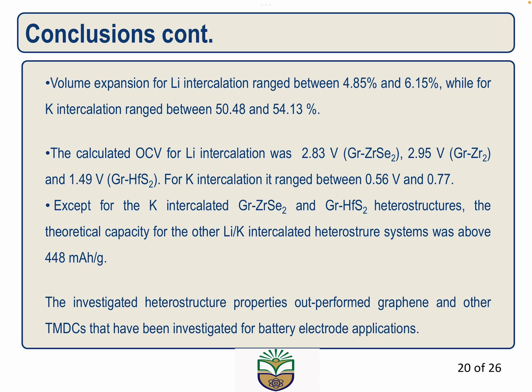The other study involved the volume expansion, and we were able to demonstrate that the lithium intercalation lay between 4.85 and 6.15%, while that of potassium lay between 50.48 and 54.13%.